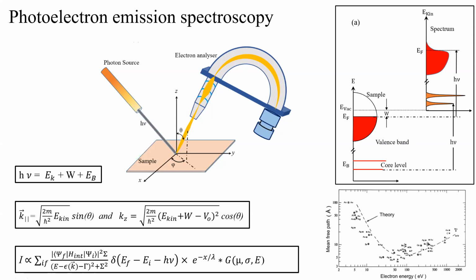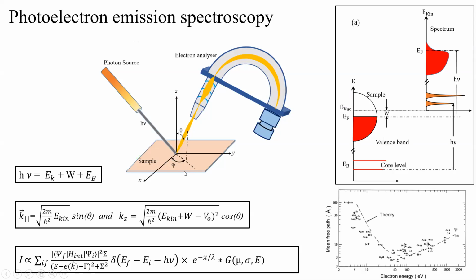The third part is this exponential, e to the power minus x by lambda. This basically comes due to the electron inelastic escaping. When you are exciting an electron say x distance from the surface, it will have to travel that much distance to come out from the sample. And while traveling that distance, it can get scattered from other atoms, impurity atoms or electrons or something else. That way it can lose the information, it won't be able to come out, or even if it comes out, it will give a background. So the probability that it will be able to come out will be e to the power minus x by lambda. It's basically a Poisson distribution, where lambda is the electron mean free path.